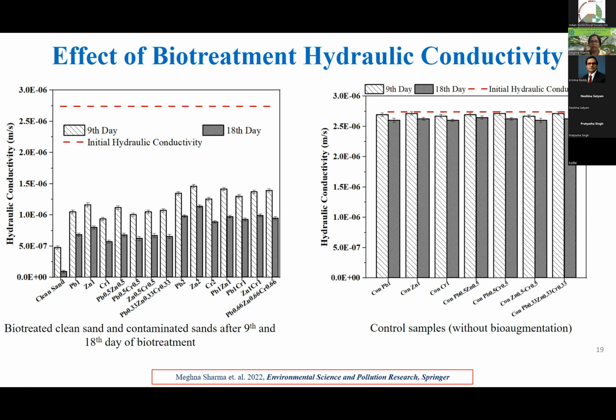That's why the hydraulic conductivity reduction was less in zinc, and in chromium it was higher, and in lead it was intermediate. And also the concentrations 1000 mg per kg and 2000 mg per kg, there is a difference. Okay, 2000 mg per kg is a higher amount of contamination. So if it affects the bacterial growth, there is lesser reduction in permeability.